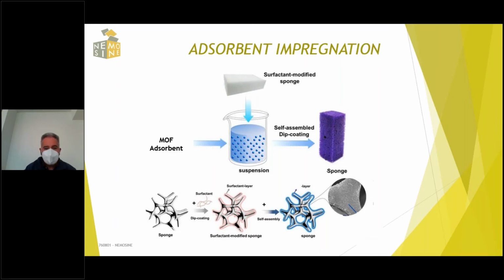Finally, in a dip-coating process of the surfactant-modified sponge in the liquid where we have dispersed the MOF sorbent, we make a process of self-assembly, and we finally have a sponge with an impregnation of MOF. At the bottom, we can see the process that the sponge undergoes. First of all, we make a treatment by dip-coating of the sponge with the surfactant. We have a surfactant layer on the surface of the foam, and finally, through a self-assembly process, we have the final coating of the surface of the sponge with the MOF material.